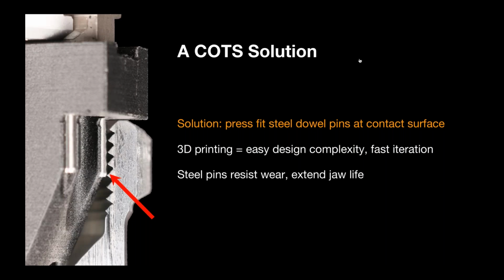So instead of printing with just the nylon, we created cavities to press fit dowel pins, just like the gripper jaws we looked at earlier, where we designed in cavities for key inserts as wear surfaces. We're doing the same thing here. We're designing cavities to press fit steel dowel pins that you can get off the shelf, so that now those dowel pins are the wear surfaces, extending the jaw life.